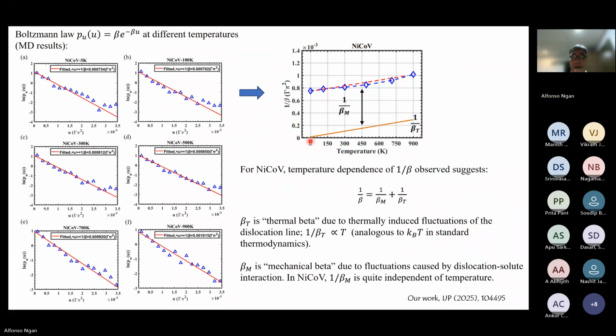So if we look at this 1/beta at various temperatures for this particular alloy with a strong pinning atomic species, the mean energy rises with temperature, but with a rather constant slope. So we can actually break this down into two components. One is a mechanical component, which is the same at different temperatures. And then the other component is linearly rising with temperature, which is our usual thermal fluctuation.